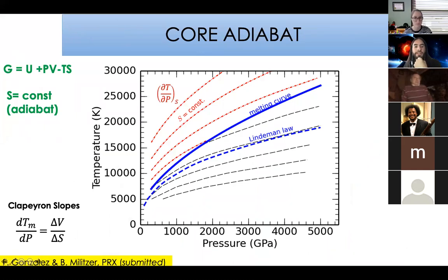We calculated these isentropes and the melting line, which is here. And the first thing we find is that we are in the first case, where we have a shallower slope. So the crystallization of super Earths should start from the center, as it happened with the Earth. And the second thing we found is that the melting curve is way above extrapolations from previous predictions, which means that iron is much harder to melt than previously thought.